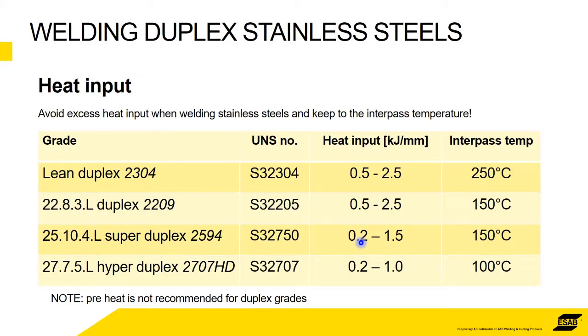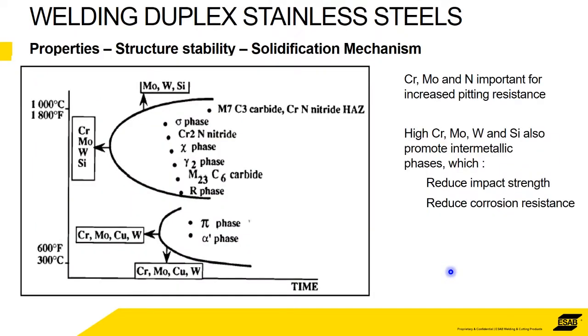Okay. In terms of heat input, basically we'd recommend as low as possible, even down to 0.2 kilojoules, which is really, really low. Obviously, you still need to weld, you still need to get fusion, but keep the heat as low as you dare. So obviously, the more highly alloyed, as we go from lean to duplex to super to hyper, the less heat that we recommend putting in there. And really, this is why.